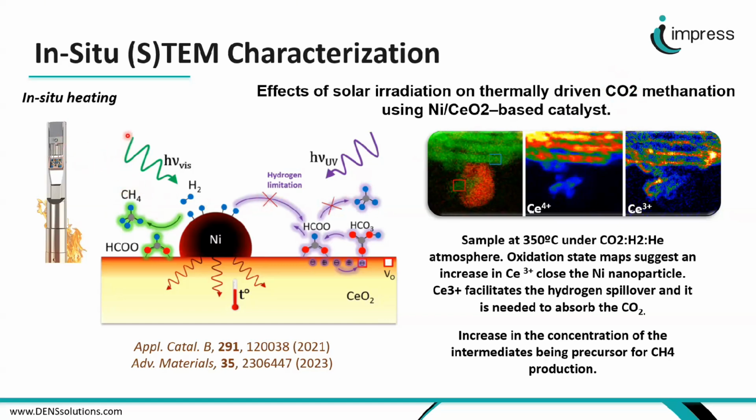In this system, solar light hits the nickel nanoparticle, and thanks to this photocatalytic reaction, the nickel nanoparticle increases its temperature due to the strong damped localized surface plasmons generated on it. At that point, there was not the possibility to do a photocatalytic reaction with a photocatalytic holder specifically, so what they did is use in situ heating to reproduce this increment of the temperature.